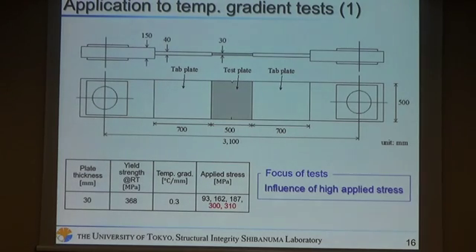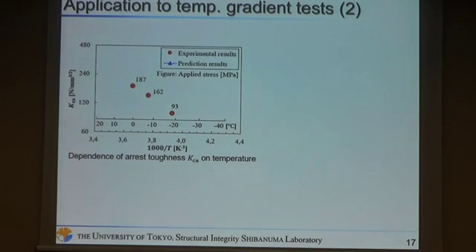The first validation is application to the temperature gradient test. The specimen configuration is shown in this figure, and this table shows the specification of the test plates and test conditions. The focus of the test is the influence of high applied stress. This graph shows the relationship between KCA and temperature at the lowest three levels of applied stress. We can see these results fit the empirical curve. However, the results at the highest level show a deviation from the empirical curve.